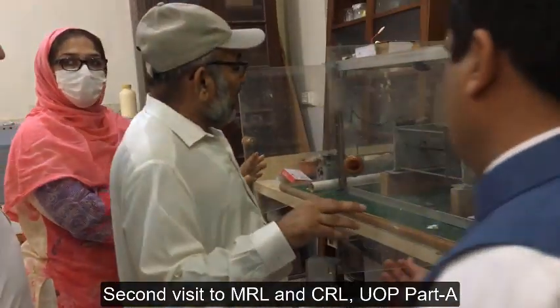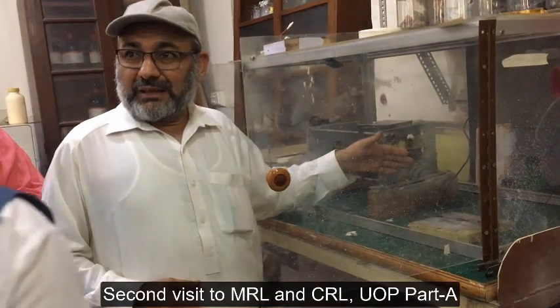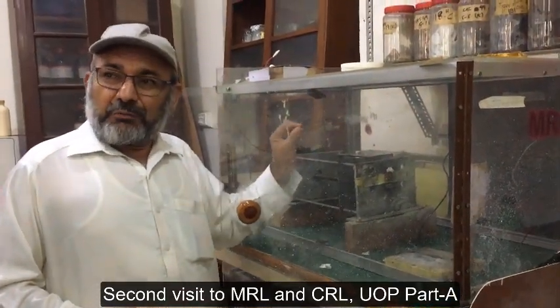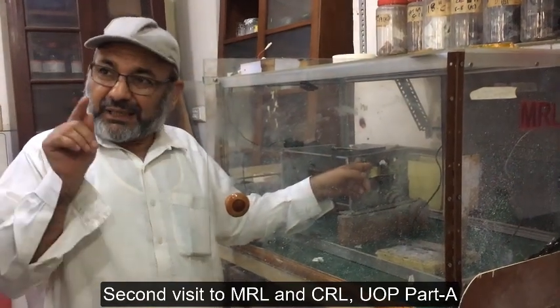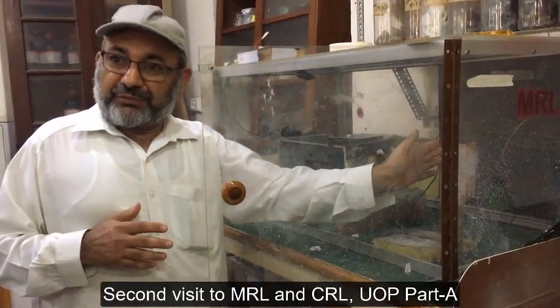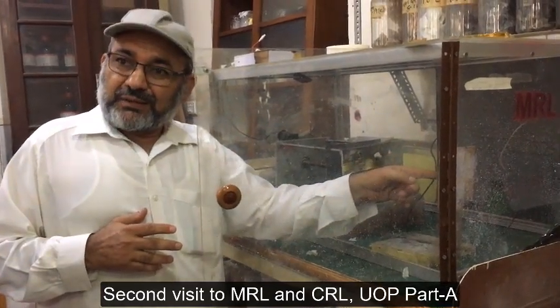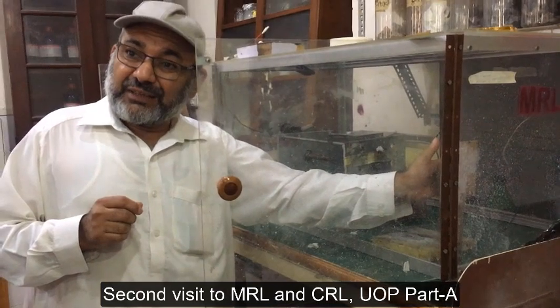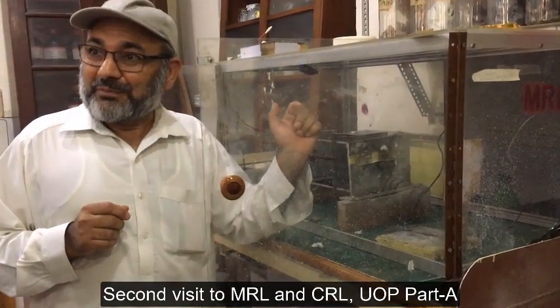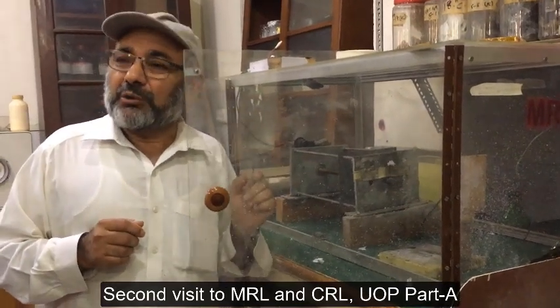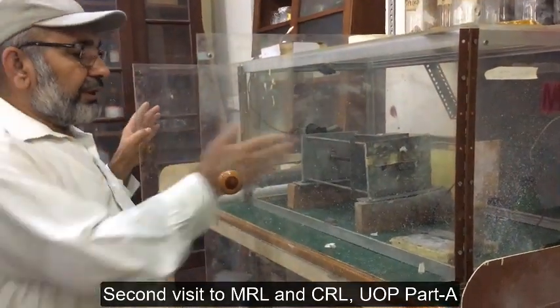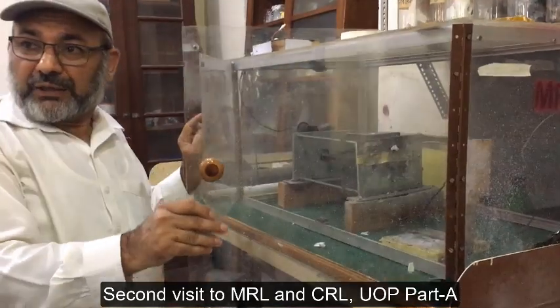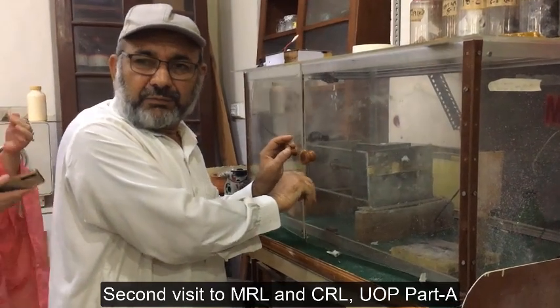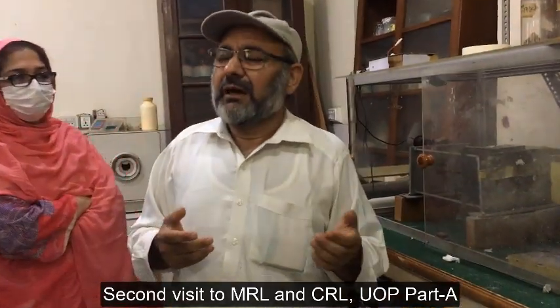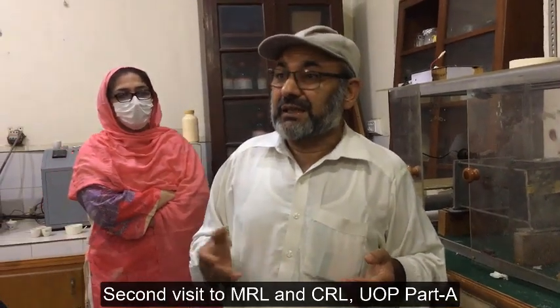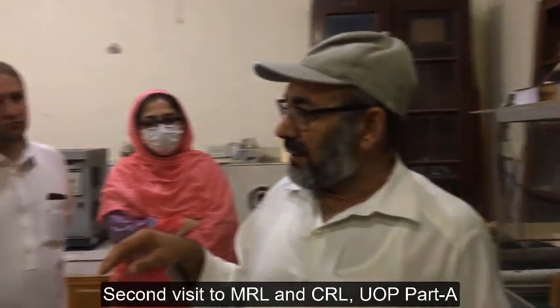This is actually a very simple electrospinning unit, right? Here we have a medical syringe, and it is pressed from that side. Fine droplets gather at the tip of the needle, and there is a huge electric field, and that electric field pulls those droplets, and they are collected here, and then we dry them, and they are nanofibers. So it is that simple a technique, but a very high voltage power supply is needed, and we usually fit here an aluminum foil, so the nanofibers are gathered on that foil. The nanofibers prepared are composite nanofibers because they have a binder in them, they have the other compositions in them.